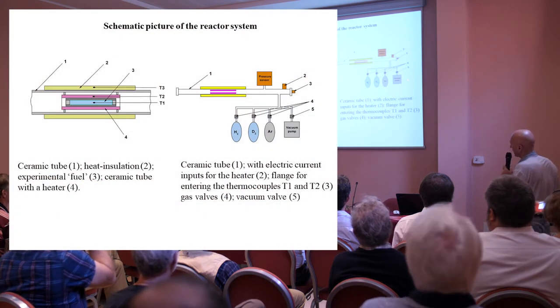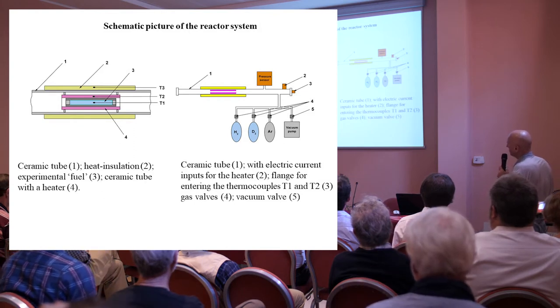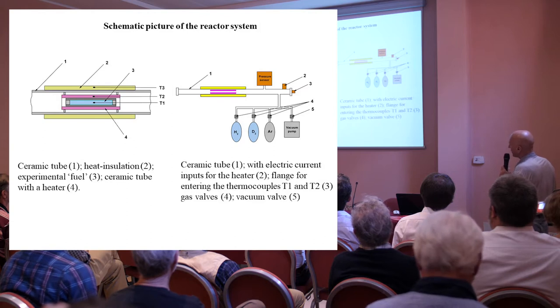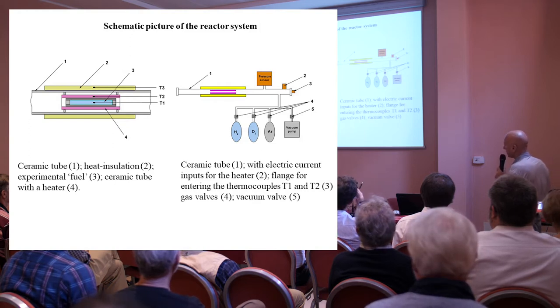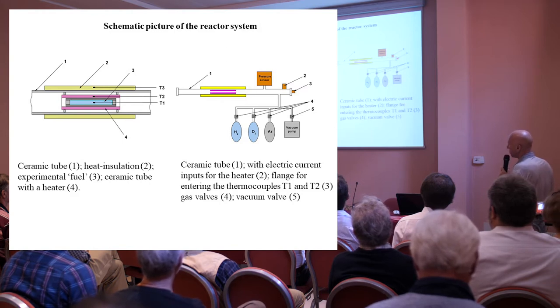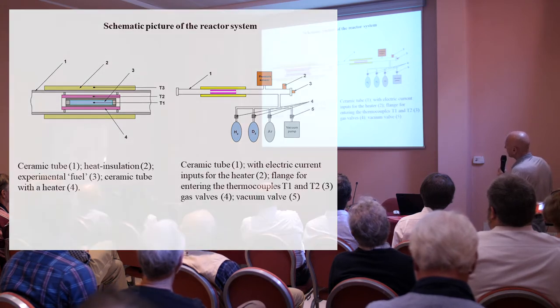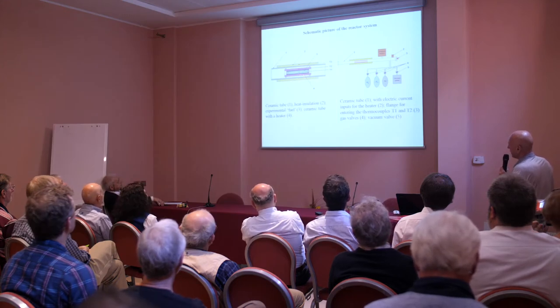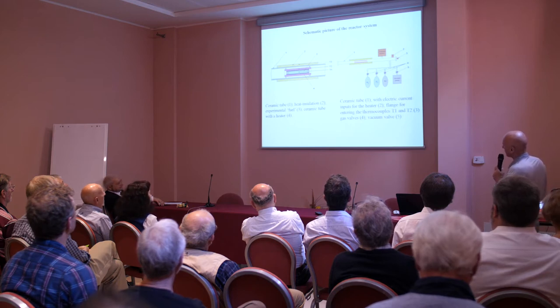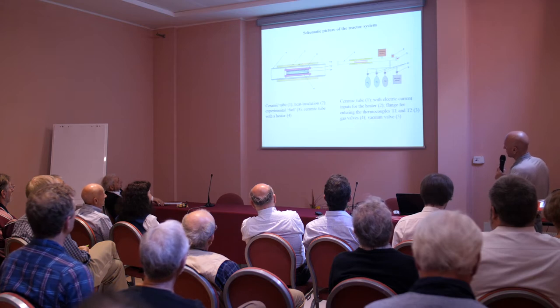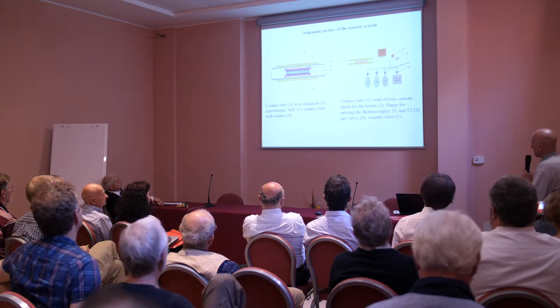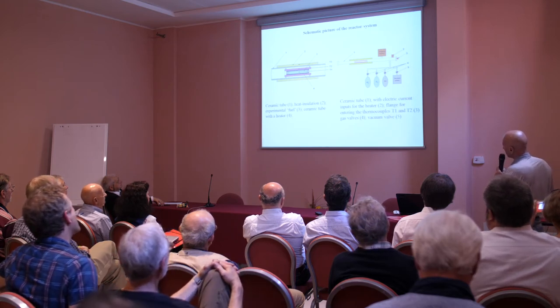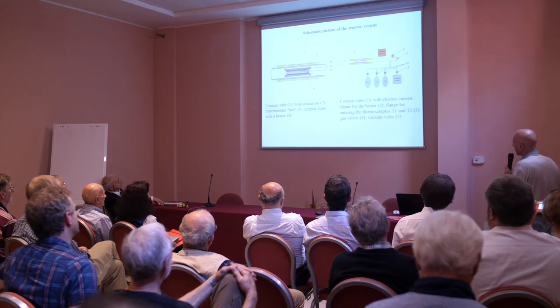Here are the schematics of our installation. It's mostly tubes. Inside is a ceramic tube with the fuel, and there's another tube with a heater. Its coils go in this way, and there's a molybdenum foil, which provides more homogeneous heating. And here is one of the thermocouples, which measures directly the temperature on the heater. Another thermocouple, T1, measures the temperature inside the fuel. And in the first installation, there was a third one, which measures the temperature just outside the outer tube. And we have the possibility to change the gases: hydrogen, deuterium, also argon, for comparison.